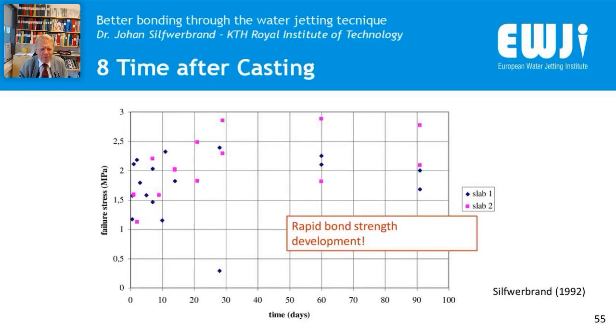And this slide is from some tests where you can see the development of bond strength. If you have a water-jetted surface, it is very, very fast. There is a lot of scatter, I admit, but you can see that already after 24 hours, 1 day, we exceeded 1 megapascal in bond strength. And this is beneficial, because then we know that you can use your repaired structure quite early after casting the concrete, because the development of bond strength is so rapid. It is much more rapid than the development of compressive strength.